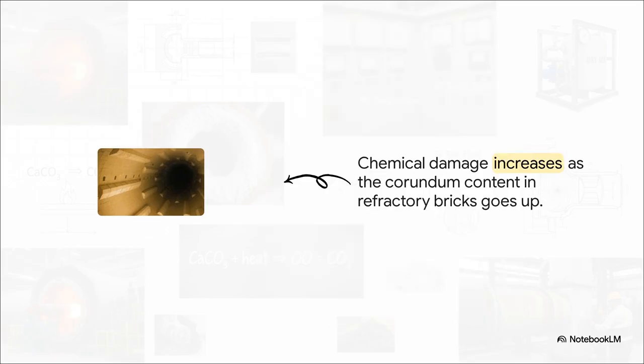You know, when you're selecting refractory bricks, it's tempting to think, just get the highest alumina content, that must be better. But it's not that simple. Look at this data. For both 60 and 70% alumina bricks, the chemical damage actually gets worse as the corundum content goes up. The real key is the mineral structure. You want a brick with a higher mullite content. That gives you much better resistance to the chemical attack from sodium. It's a perfect example of how deep material science has a direct impact on plant reliability.